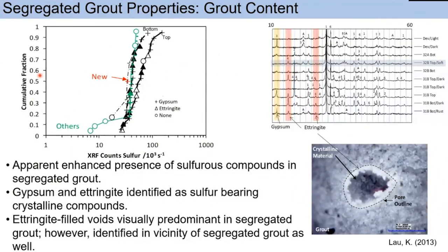Here are the XRF and XRD data compiled relating to sulfur containing compounds, as shown in these graphs. This is XRF and this is XRD. Here we can see the gypsum and ettringite. High sulfate concentrations were measured in the grout pore water and were further supported by the identification of ettringite in the macro pores of segregated grout. Gypsum and ettringite were identified as sulfur-bearing crystalline compounds. These black data show the actual breach sample data. At the top, the sulfur is more than at the bottom one.